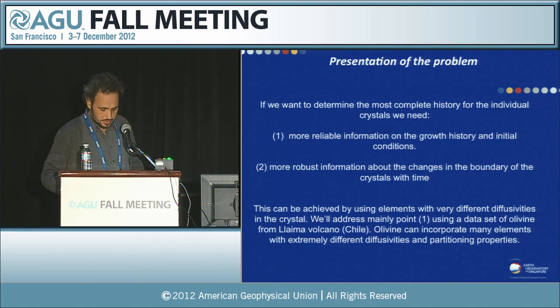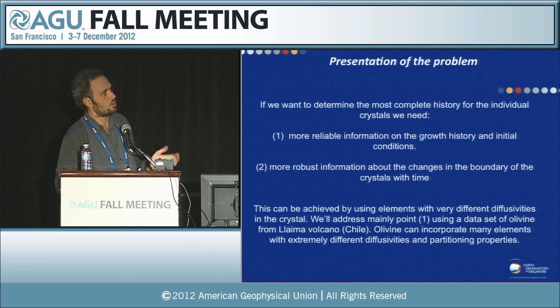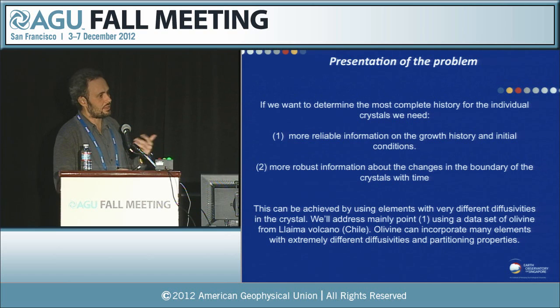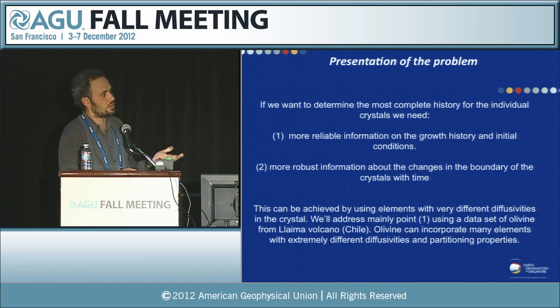So the idea is, okay, what can we do with these elements if they're completely homogenized? What we can do is look at other elements, notably here phosphorus, that diffuse much slower, and use this to get more reliable information about the growth history, initial conditions, and also hopefully the boundary. This presentation will focus mainly on this part. We have started to work with this part, and I'll show you at the end some of what we have started to do. But mainly it will be the growth history.